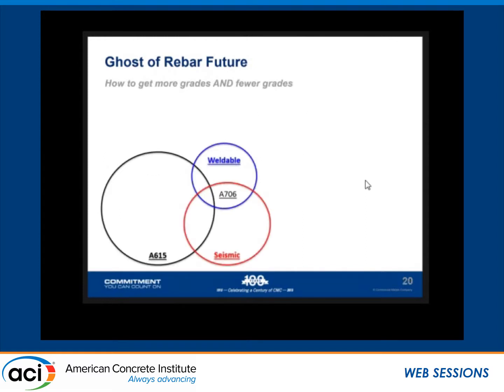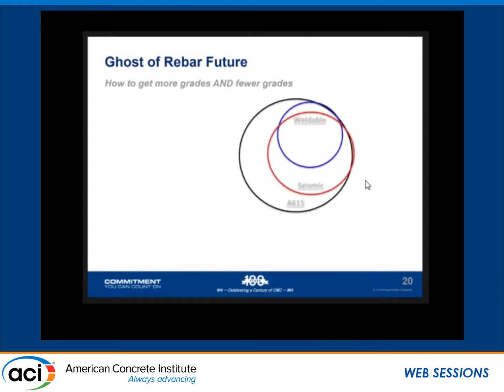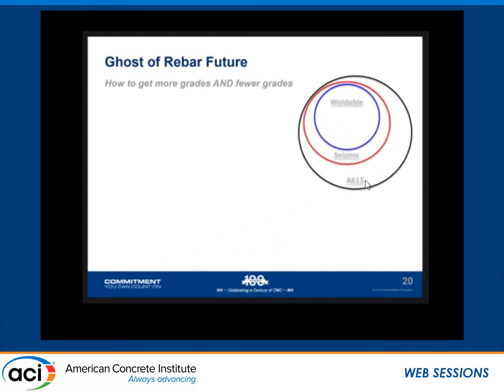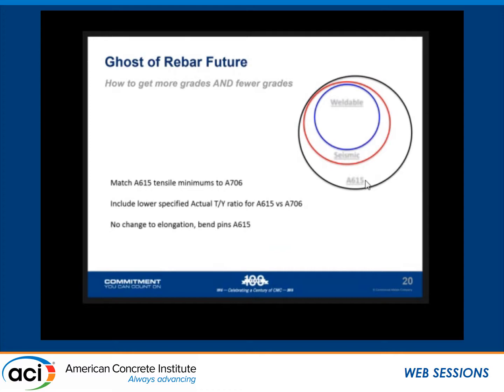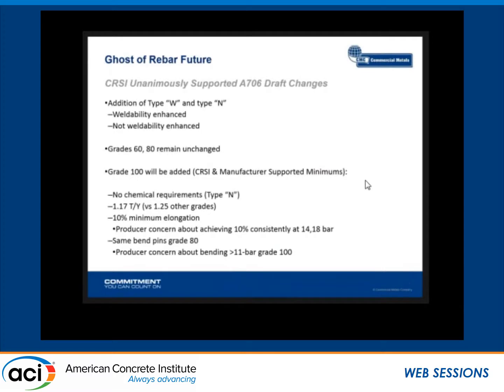So real quick, how do you get more grades and fewer grades at the same time? You redo the grades so that they line up. That way, at least if you hit the one in the middle, you hit them all. What that means is we would have to match A615 to A706, probably put a lower tensile to yield ratio in, no changes to elongation, but bring that tensile minimum down. That would greatly solve a tremendous amount of issues in the marketplace and on the design side.